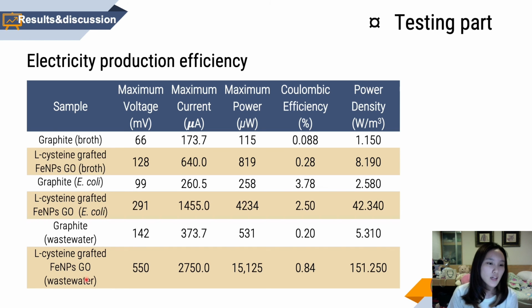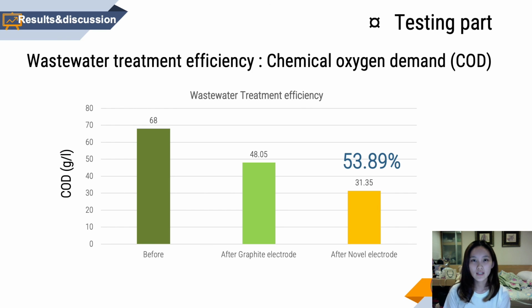You can see that in wastewater, the max current of our novel electrode is about 7.6 times compared to the graphite electrode, and the max voltage of our novel electrode is 550, which is 3.9 times compared to the normal one, and the power density is about 28.5 times. Lastly, for the wastewater treatment, the results suggest that our novel electrode can actually treat wastewater by decreasing chemical oxygen demand values by almost 54%.